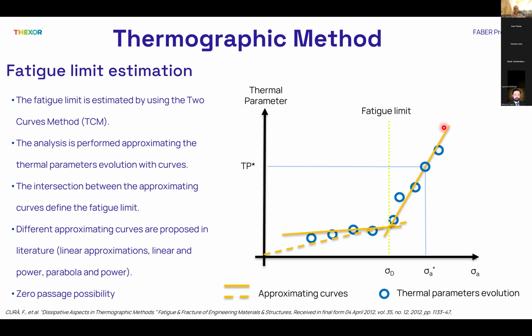Another possibility is the parabola power law approximating curves, meaning the thermal parameters evolution below the fatigue limit is approximated using a parabola mathematical formulation, while the evolution above the fatigue limit is approximated using a power law mathematical formulation.